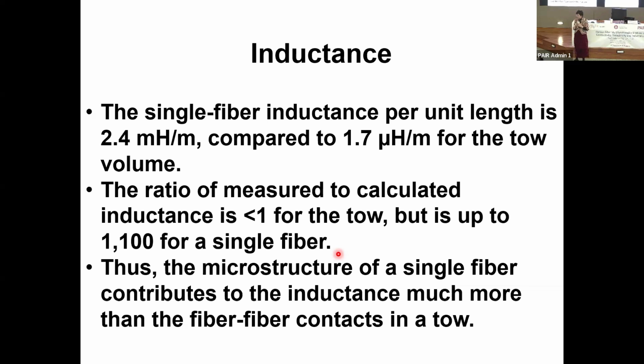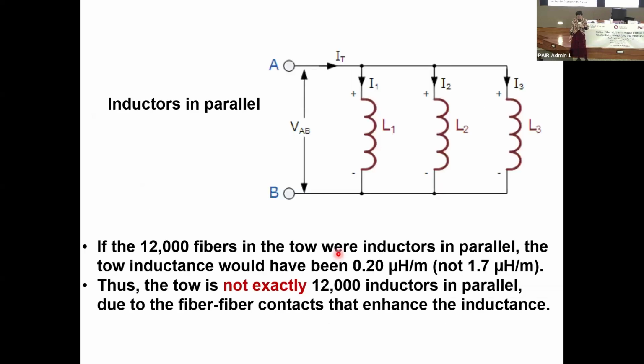So it's a difference by 3 orders. The ratio of the measured to calculated inductance is less than 1 for the tow, but it's up to 1100 for a single fiber. So the microstructure of a single fiber contributes to the inductance much more than the fiber-fiber contacts in a tow. Now, if the 12,000 fibers in the tow were inductors in parallel, the tow inductance would have been only 0.2 microhenry per meter, not the 1.7.